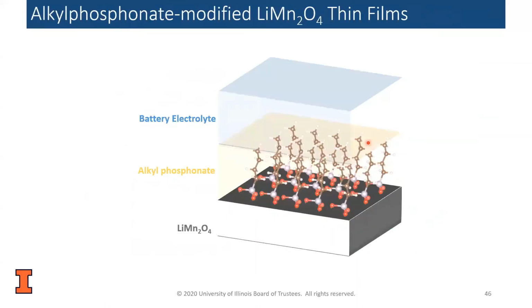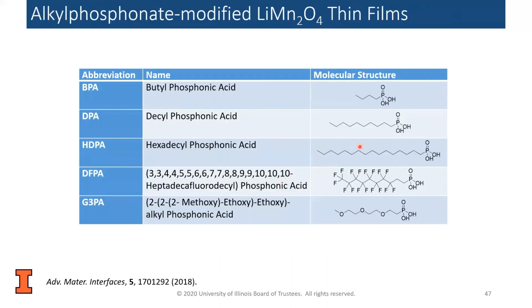So in the next examples, I'll show some oxide electrodes. In this case, it's just LMO, lithium manganese oxide, that is coated with a variety of different self-assembled monolayers. And so these monolayers were fabricated to have different chemistries. As I mentioned earlier, the metal oxides will have a hydrophilic surface. And so we picked a variety of SAMs that had both hydrophobic of different types and a hydrophilic variety. And so also we varied the chain length and also the functional group, substituting fluorine for hydrogen.